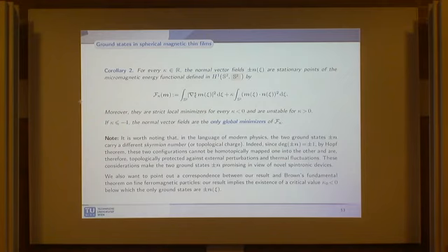Because what we do is compute the second order variation, and then via the sharp Poincaré inequality, you can see that for kappa less than 0, the second order variation is greater than or equal to some constant times the L2 norm of the vector fields. But still, this is a local minimizer in H1. And then you can see that these are unstable for kappa greater than 0. So you do an analysis on the second order variation, having a sharp inequality to play with.